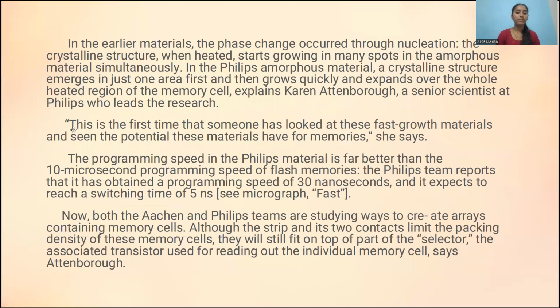In the earlier materials, the phase change occurred through nucleation. The crystalline structure, when heated, started growing in many spots in the amorphous material simultaneously. In the Philips material, a crystalline structure emerges in just one area first and then grows quickly and expands over the whole heated region of the memory cell, explains Karen Attenborough, a senior scientist at Philips who led the research. This is the first time that someone has looked at these fast-growth materials and seen the potential these materials have for memories.